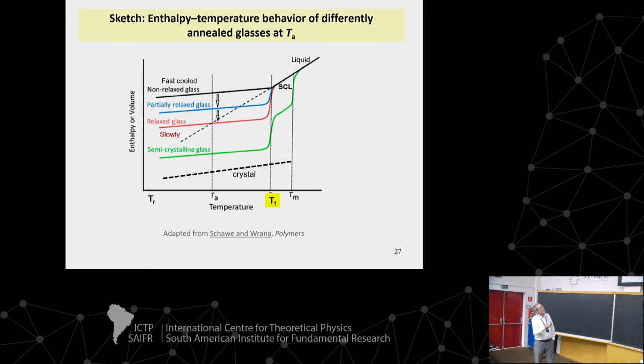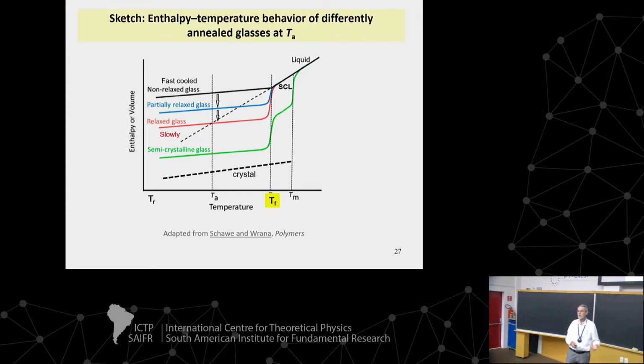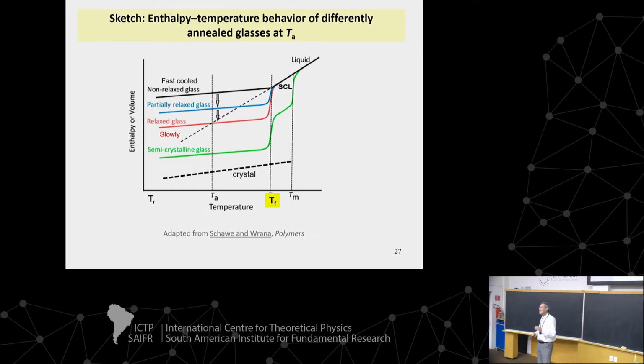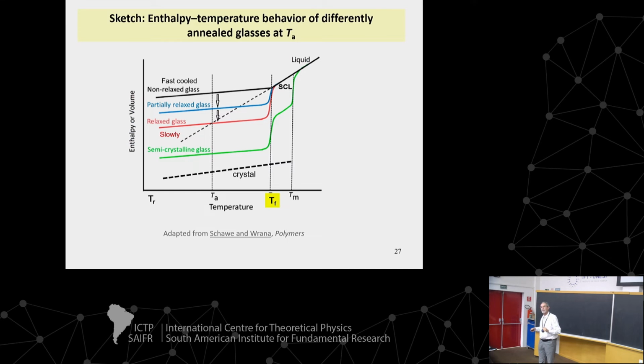Let me try to give my view on this, although not everybody agrees with my definition. Well, you have a liquid. If you are above the melting point, for any substance, the liquid state is the thermodynamically stable state. Take water, above 0 degrees Celsius at normal pressure, the stable state is liquid. If you cool down a liquid, any liquid will love to crystallize below the melting point to reach equilibrium. But you can cool a liquid fast enough and avoid crystallization. That's the whole idea. So you can freeze the liquid structure without crystallizing, and that's a glass. It's a temporarily frozen material, without crystallizing, which has the structure of the isochemical liquid.